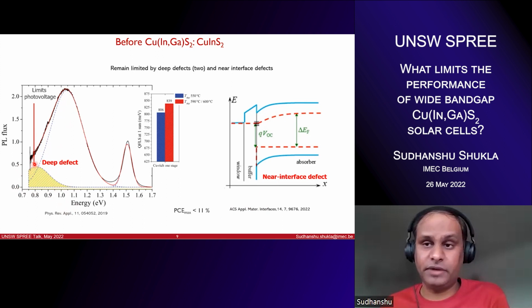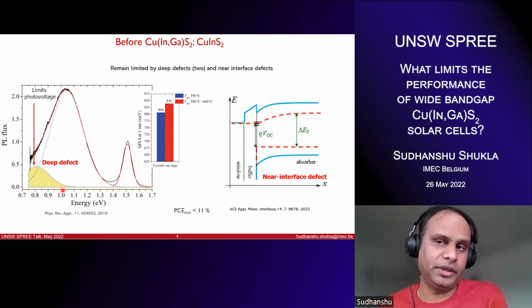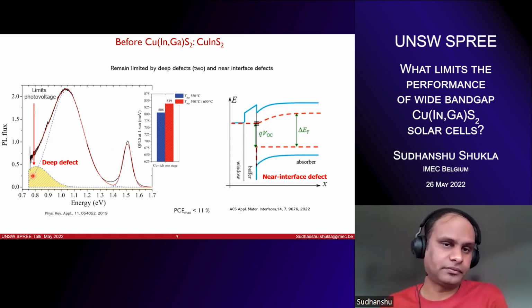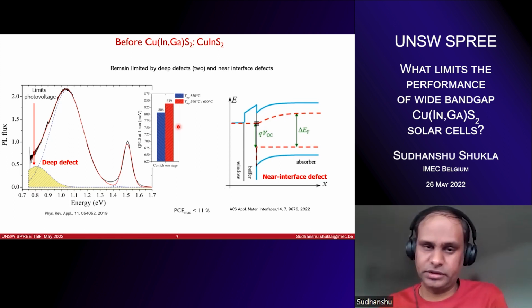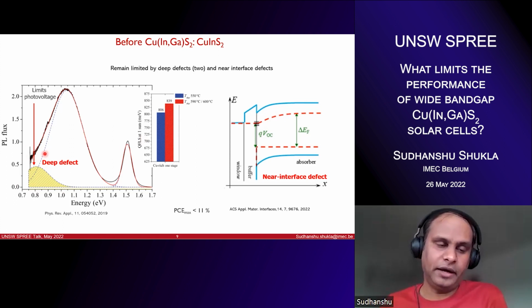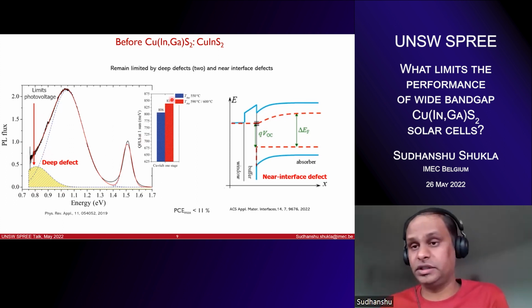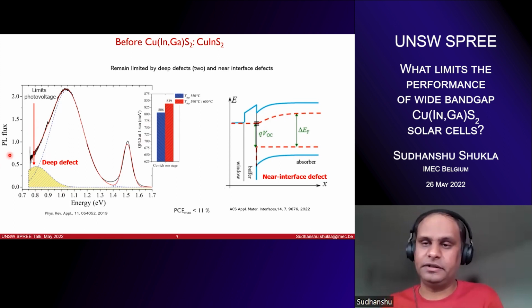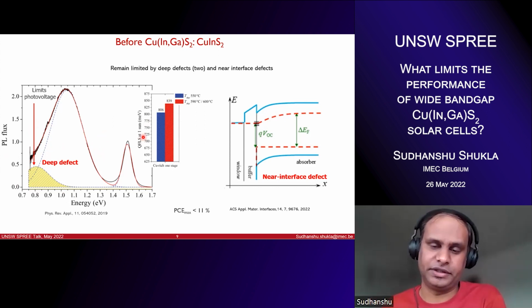So even if you passivate it, the next defect that you have to deal with will be this one. That will then become the dominant factor that will limit your VOC. We have actually suppressed it; we showed it previously. In this reference by my colleague, if you increase the growth temperature from 550 to 590, the quasi-Fermi levels actually improve. I'll come to what quasi-Fermi level splitting is later on. And you have the suppression of deep defects. So this is one strategy for how you can passivate these deep defects: playing with the temperature and active passivation, for example.